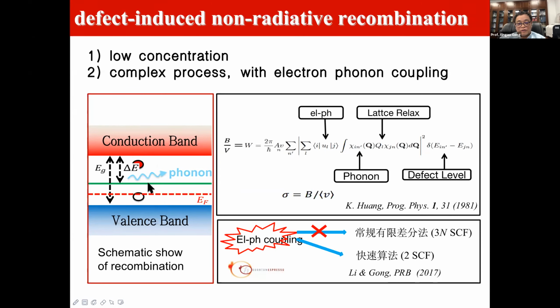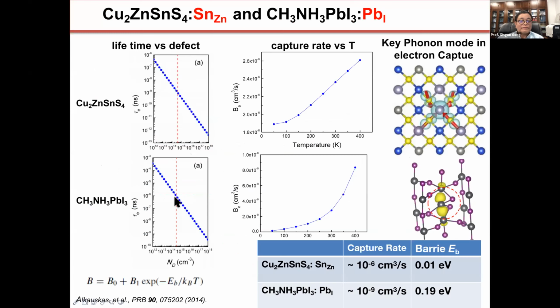This is important. Usually in semiconductors, there are many defect levels. These defect levels will kill these electron holes. So one needs to calculate and study the lifetime of the electron-hole pairs. One needs very complex calculations. These kinds of formulas were actually known 30 or 40 years ago, and they need the electron-phonon and lattice relaxation. But to do real calculations is still not so easy. So I'd like to show one last example, and for this